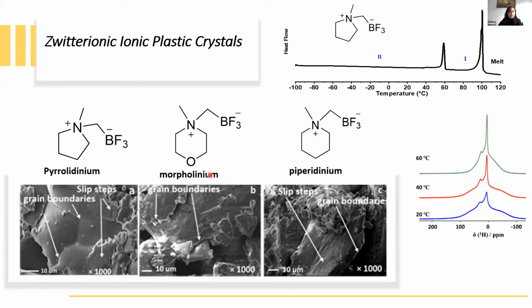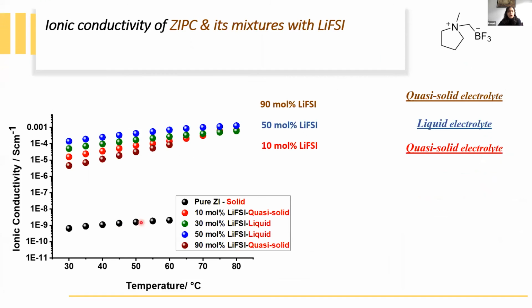Based on a variety of techniques, like a combination of morphology studies, thermal phase behavior, and NMR characterization, we found that there is a sufficient degree of disorder in the structure of these materials that, like plastic crystals, can provide fast target ion conduction within the matrix. So we can use these materials as a matrix electrolyte and add target ion into them. As an example, I'm talking about the pyrrolidinium one. We added different concentrations of lithium salt into the pyrrolidinium zwitterion, and the ionic conductivity of the mixtures at all concentrations is relatively high.